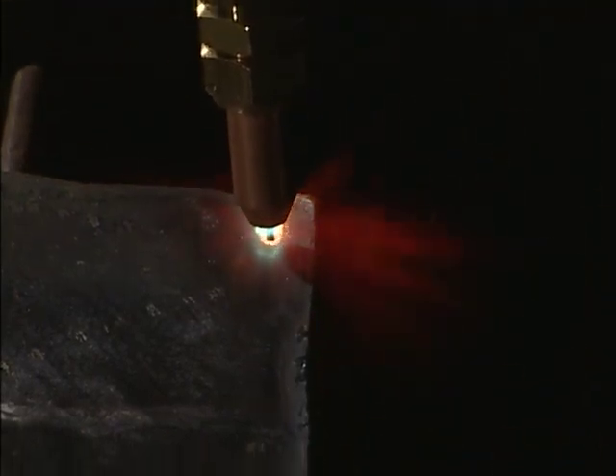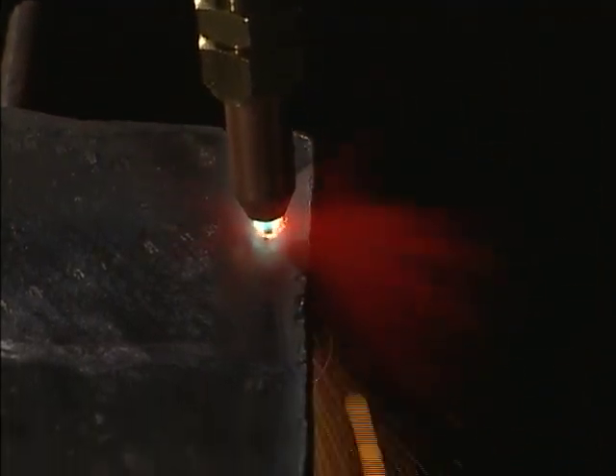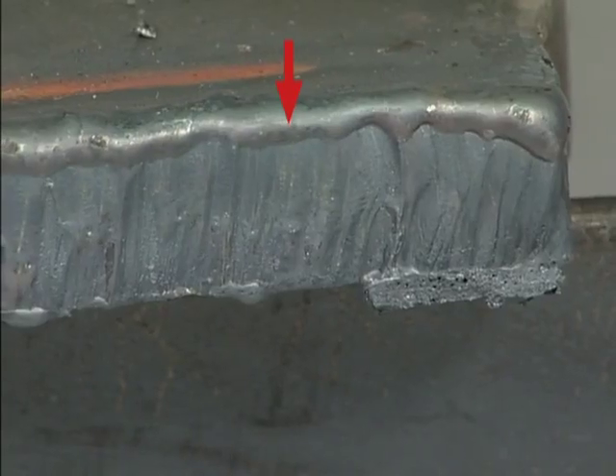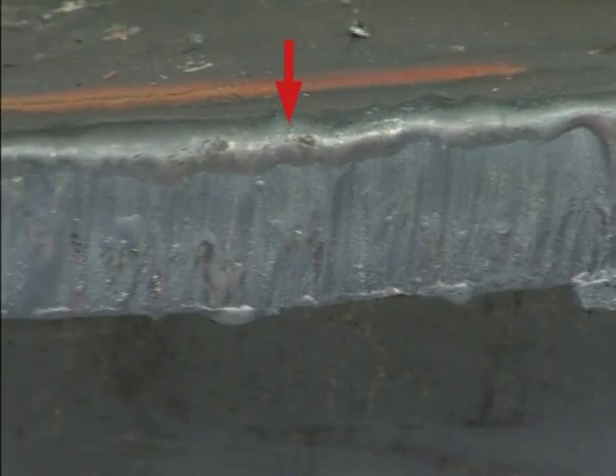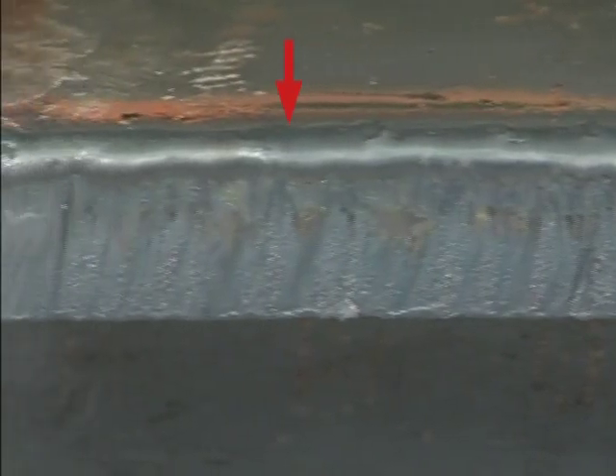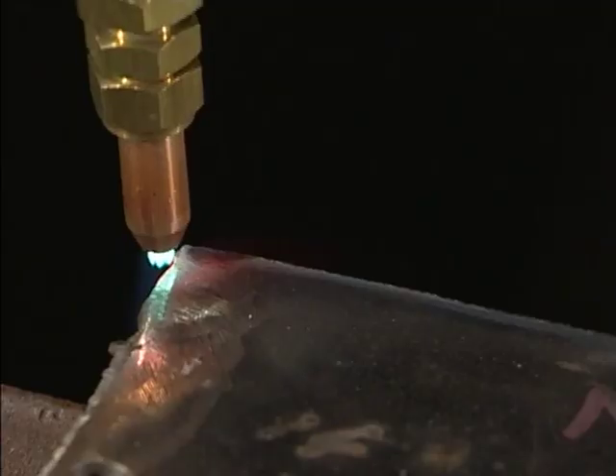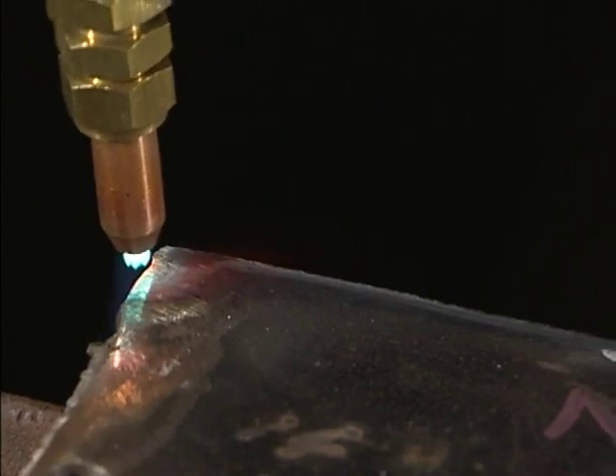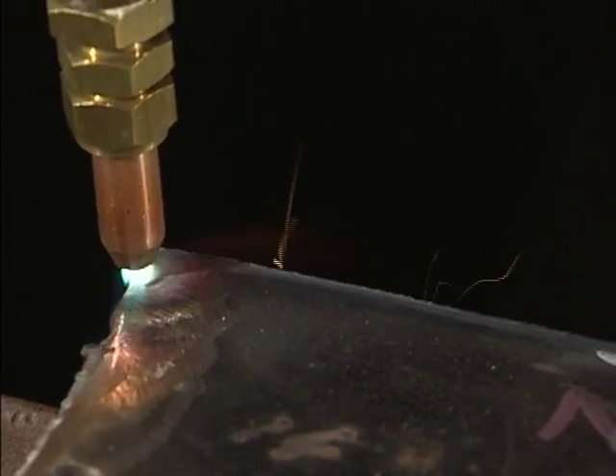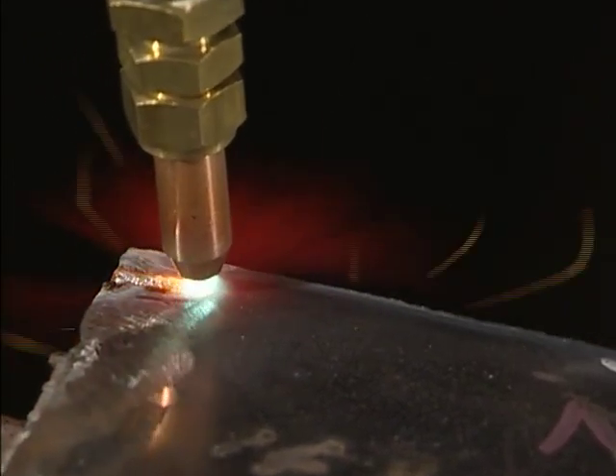To guarantee high-quality cutting, proper preheating must be conducted using a preheating flame that has a length and strength suitable for the thickness of the plate to be cut. If your flame is too strong, upper corners of the plate's cut surface melt and become round. Too weak a preheating flame may cause the cutting operation to stop halfway through.